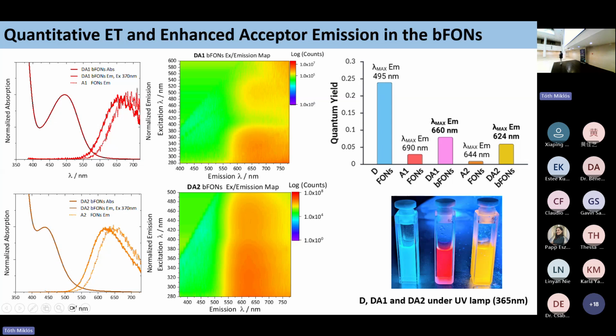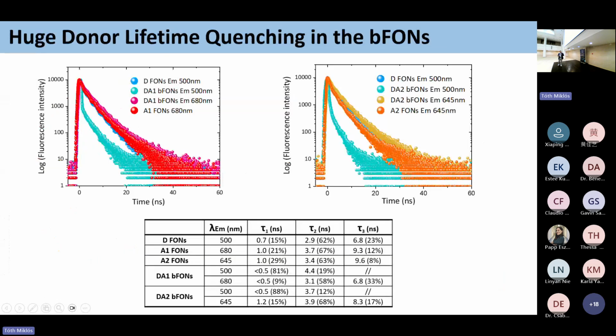And as the first good evidence from this work, by determining the fluorescence quantum yield we saw that the quantum yield of the acceptors gets enhanced in the binary nanoparticle, reaching values of 8% for acceptor 1 and 6% for acceptor 2. So there must be some collective effects that determine this quantum yield enhancement of the acceptors' emission in the mixed nanoparticles. Then we determined the fluorescence lifetimes for the dyes, for the nanoparticles, both the single component and the alloy ones, by time correlated single photon counting.